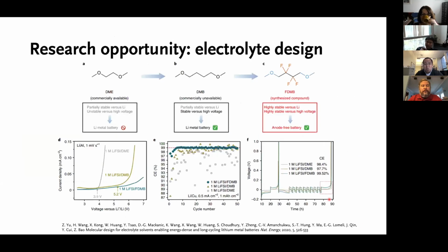So here I wanted to use one recent paper jointly published by Yi Cui's group and Zhenan Bao's group at Stanford to illustrate some of the design principles or design considerations of electrolyte. The bottom line is that when you choose electrolyte, you want it to provide good solubility, good stability. Solubility can be afforded by, for instance, polar solvents such as ether functional groups here. And in order to improve the stability, you can try to extend the linear chain of the alkyl group. And this is one principle people have followed. But the catch is that you don't want to do it too much. Otherwise, the solubility will become an issue.